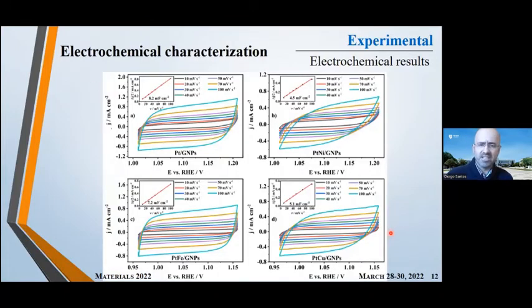We start by determining the capacitance of the materials. So this is done by scanning the potential of the materials at different scan rates. And what we do is then we check what is the difference between the positive and the negative current for each scan rate, and we plot that. So that difference that we see here from this point to this point, and we plot that as a function of the scan rate, and from that we can get the capacitance of the material. We can see here that platinum iron was the material with the higher capacitance of the three platinum transition metal alloys, and it was close to that of a platinum that we also tested, just the platinum supported on the